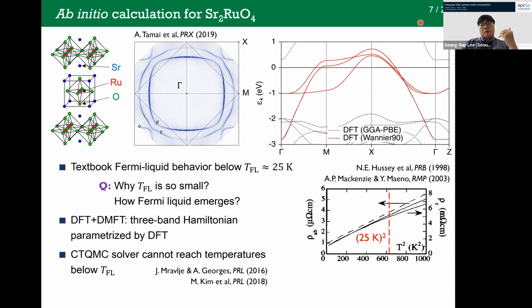So first we just run DFT and find that there are 3 bands crossing the Fermi level. The upper bands will be almost empty, and the lower bands will be almost full. So they are less relevant in the physics happening near the Fermi level. So we just take these 3 bands and perform the Wannierization to parametrize the 3-band Hamiltonian to be solved by DMFT. So we can now apply quantum many-body methods to solve this 3-band Hamiltonian.